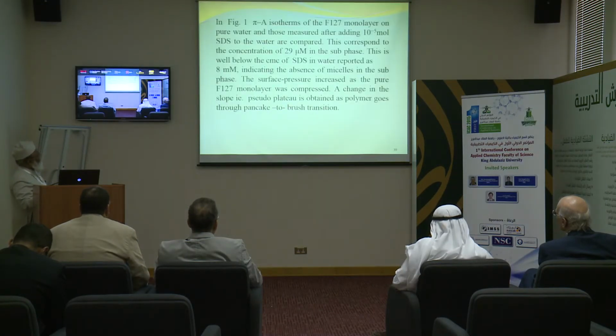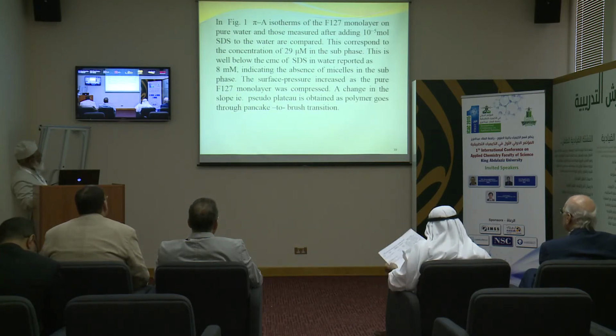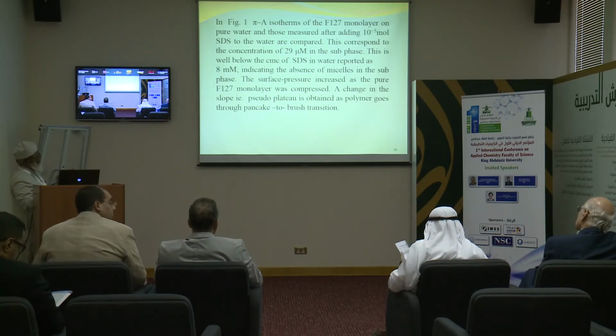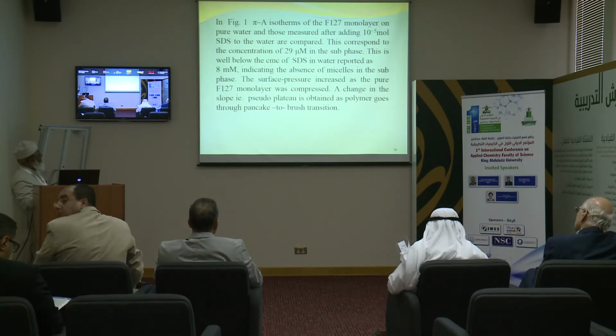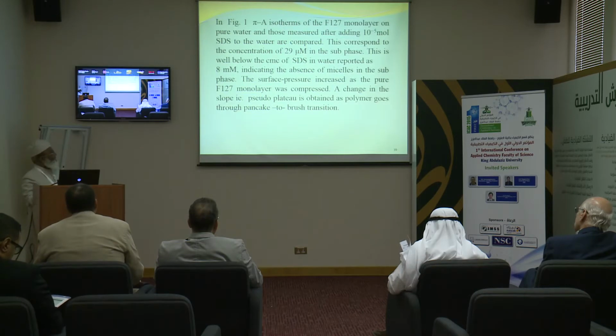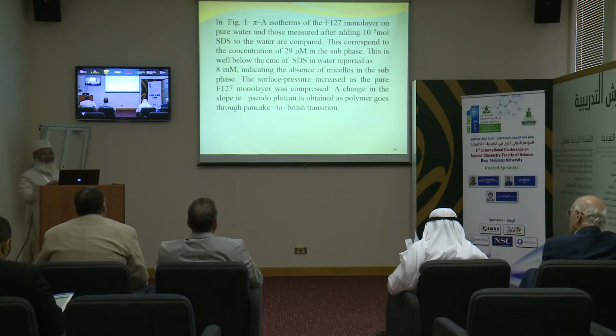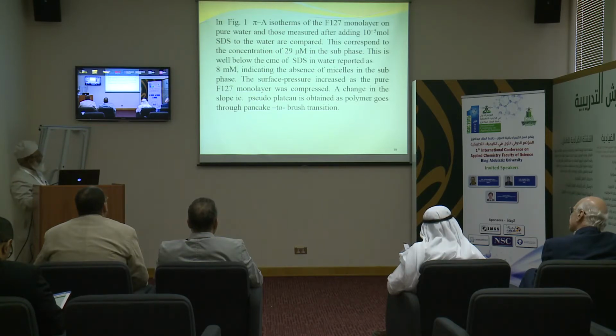Now we can observe something here: the surfactant was used as 10⁻⁴ mole of SDS added to the water, and also the curve without surfactant. This corresponds to a concentration of 29 micromolar in the subphase. This is well below the CMC, the critical micelle concentration of SDS in water, which has been reported as 8 millimolar. This ensures the absence of micelles in the subphase.